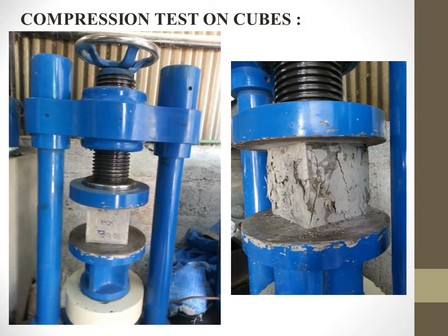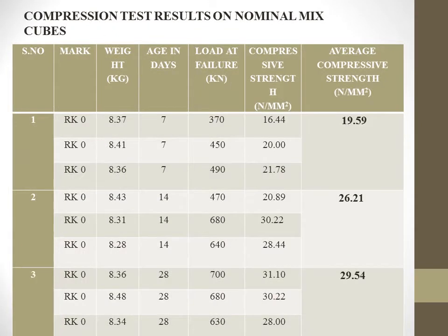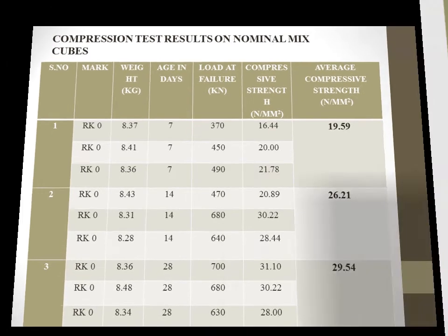We had put the cubes for compression strength test, and as you can see, the pattern of failure is here in this picture, where these are the tabulation results on compressive strength test on nominal mix cubes, that is without any fibers. We had used only the coarse aggregate, fine aggregate, water and cement, and the strength after 28 days of curing was found to be 29.54 Newton per mm square.